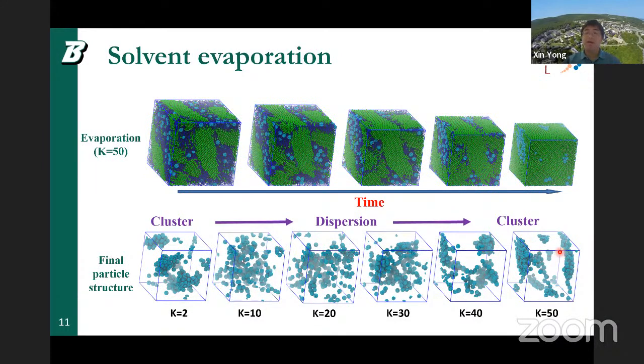However, this time the aggregation appears to be very anisotropic. And this is because we believe the polymer ordering and the orientation of this nematic region guides the aggregation of the particles, as you can see here. So this is a more isotropic cluster versus a very anisotropic, elongated cluster.